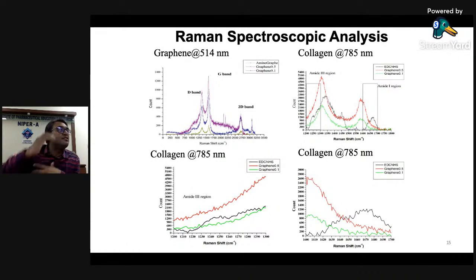This is also very informative data, telling us that as the helical content increases, the strength of the collagen also increases, and that's why probably we get better toughness in the mechanical strength. So graphene is also promoting the helical content of the material as per our cross-linking strategy.